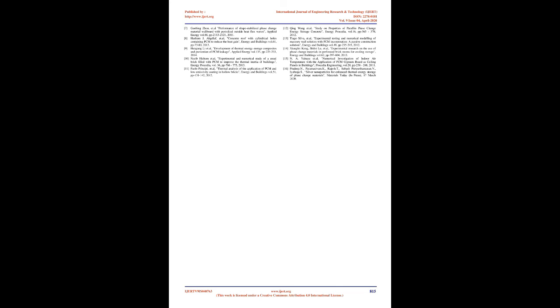G. Thermal variation from ANSYS of CM with PCMs for 4 mixes at 9 am. To find the temperature reduction in each of the model wall bricks from outside surface to inner surface, a two-dimensional analysis of brick with CM and PCM was modeled and analyzed using ANSYS software. These kinds of analysis were done and the heat flux was visualized with all mixed proportions. Fig.6 shows the thermal conductivity results outside and inside the wall at 9 am for the 4 mixes. It is seen from the graph that CMPP shows the best thermal insulation. Fig.6 Thermal variation from ANSYS of CM with PCMs for 4 mixes at 9 am.